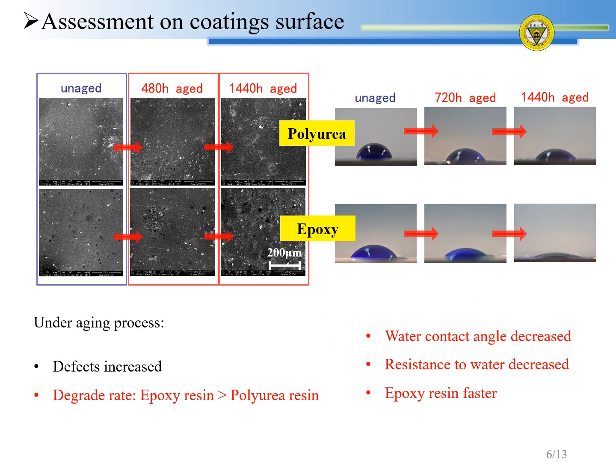After aging, let's look at the surface characterization first. Under the scanning electron microscope, we can see that, as aging goes on, more defects appear on the coating surface. The epoxy resin deteriorates more obviously. We know organic coatings usually have a good resistance to water, but under aging, this performance gets worse. It is apparent that the water contact angle decreased, and epoxy resin decreased faster.